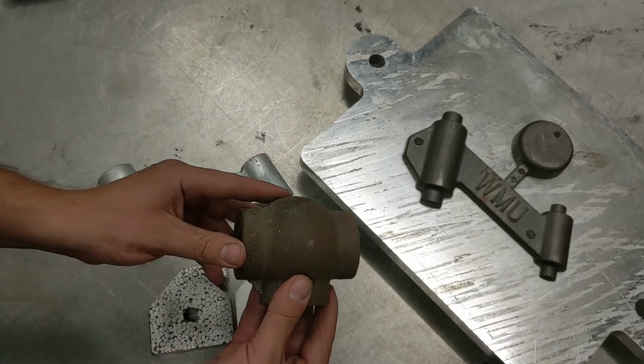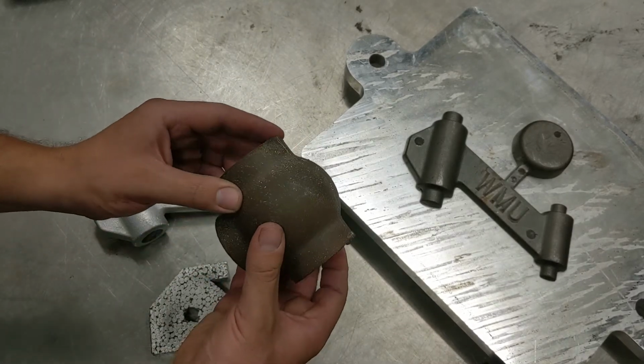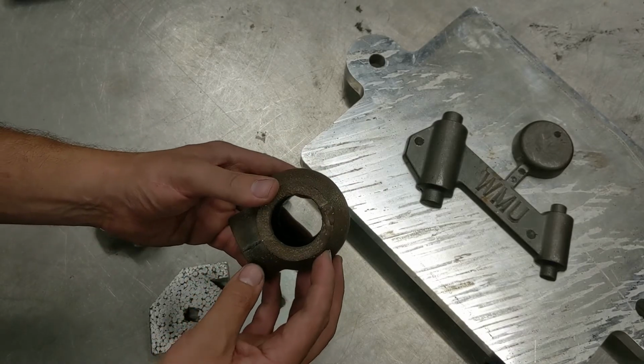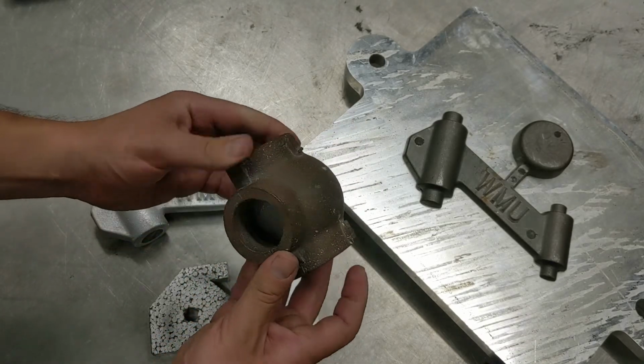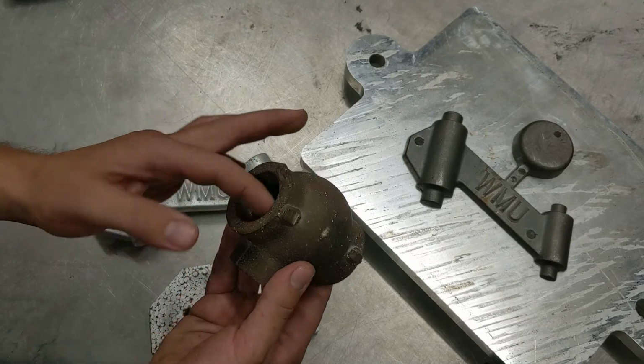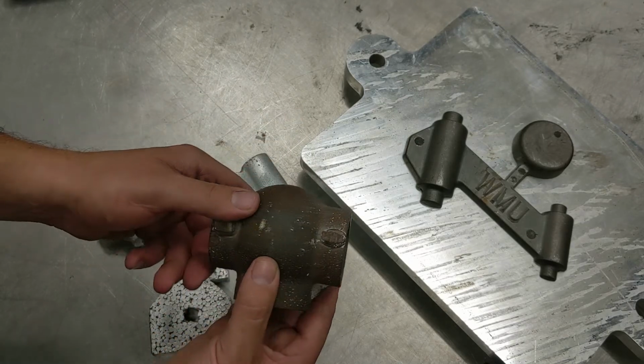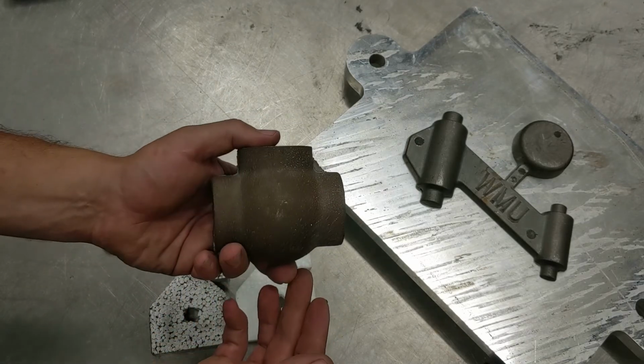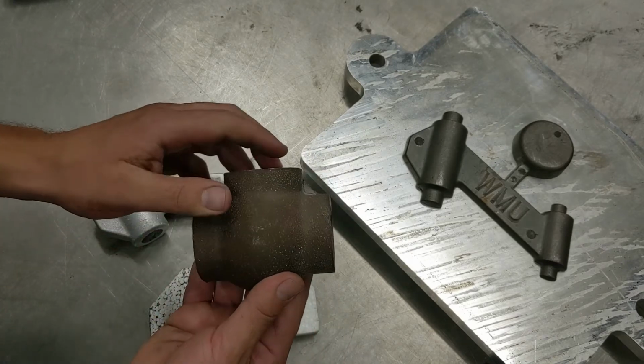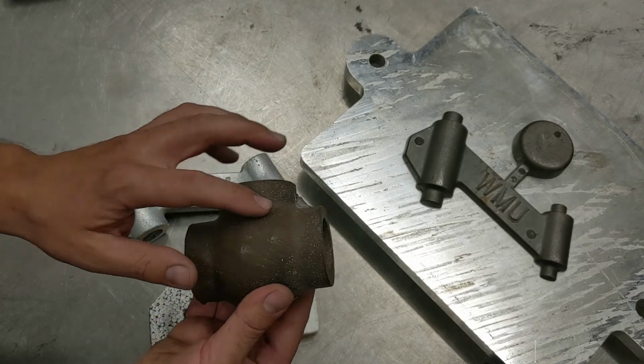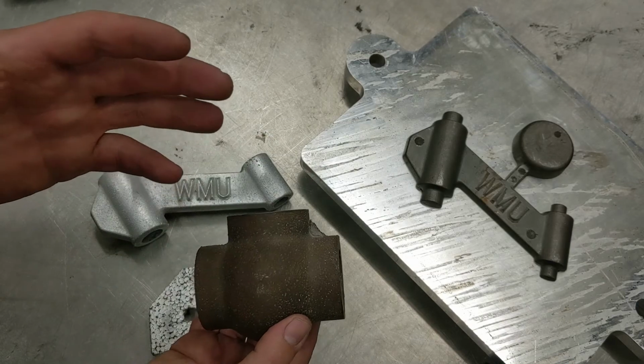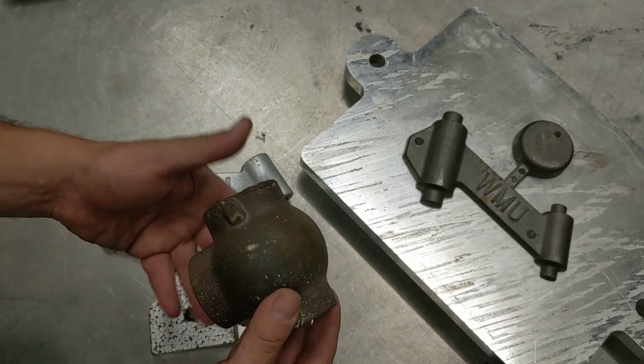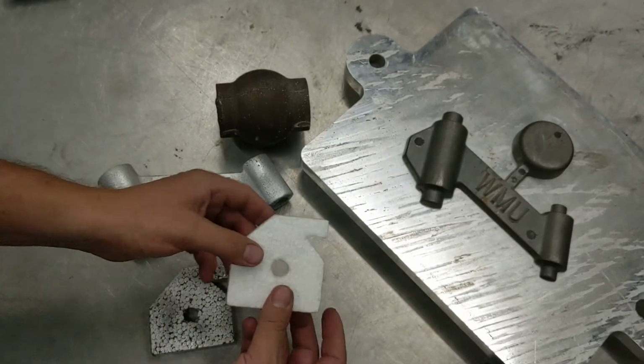I wanted to show you a consumer product that's made by polystyrene foam. This is a pipe fitting, and it's cast iron. It's made by the same process, and you can definitely see a better surface finish here. That's because the patterns for consumer products would be made in their own mold, and that would yield a better surface finish on the foam pattern in the first place,